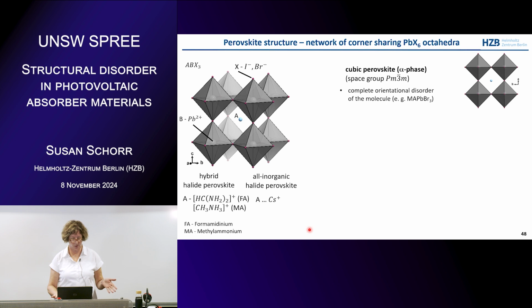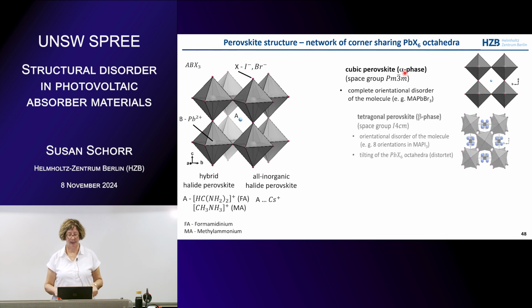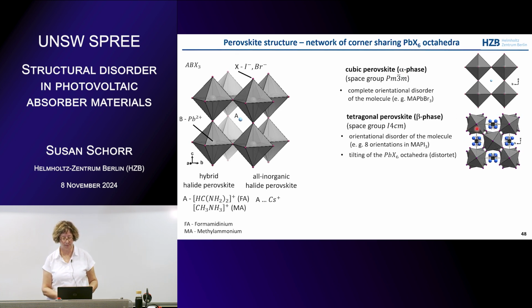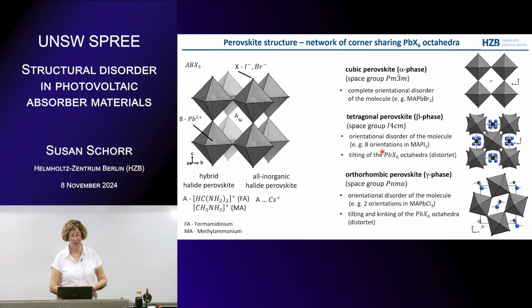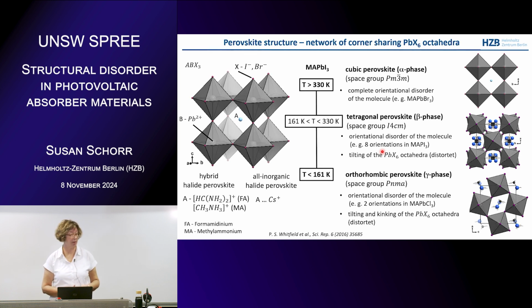Just a few slides. So some materials adopt the cubic perovskite type structure like methylammonium lead bromide, where the molecule is completely disordered. It can become a tetragonal perovskite like MAPI, where we found 8 different orientations for the molecule, or it can be orthorhombic like methylammonium lead chloride, where we have only 2 orientations of the molecule. And MAPI shows structural phase transitions. Above 330 Kelvin it goes to cubic, then at room temperature it's tetragonal, and below 161 it's orthorhombic.